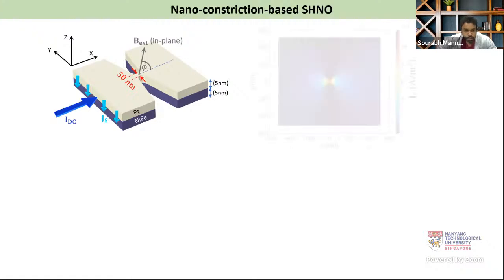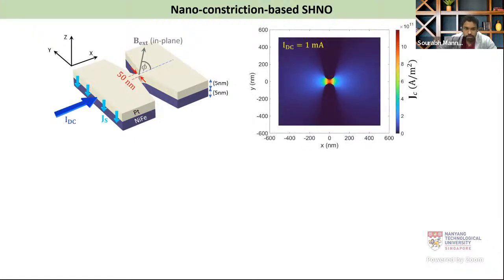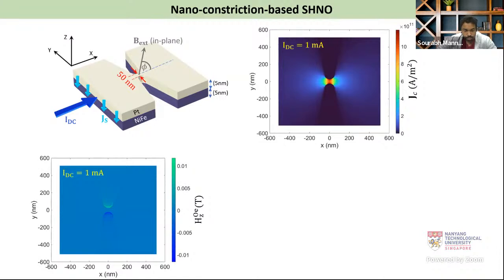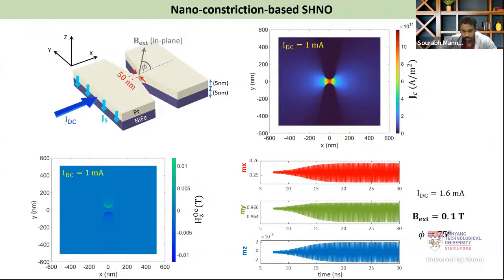So we mapped the current density distribution in the platinum layer, and we have seen that due to the spatial geometry, it has a significant non-uniformity in the current density distribution. And we also mapped the Oersted field distribution in the permalloy layer. So with all these, we have achieved the oscillation, and this is the oscillation profile for an input current of 1.6 milliampere, and the external field is 0.1 Tesla at a 75-degree angle with respect to the current.